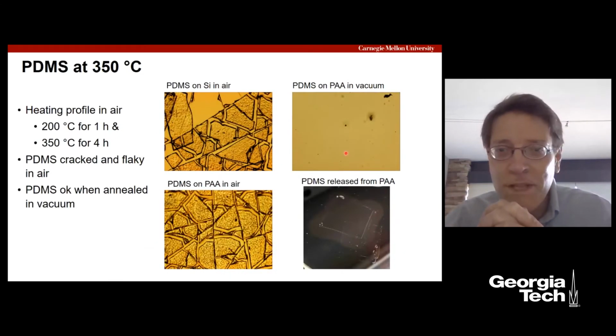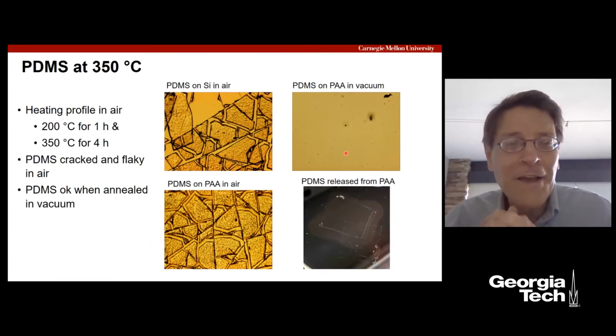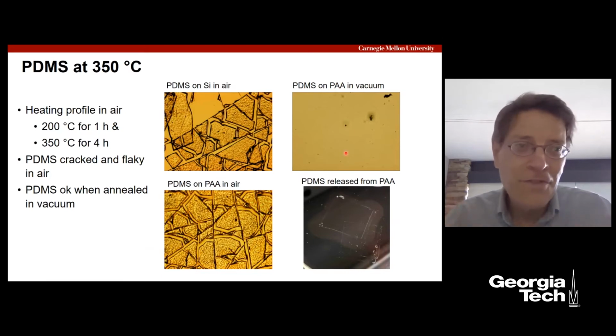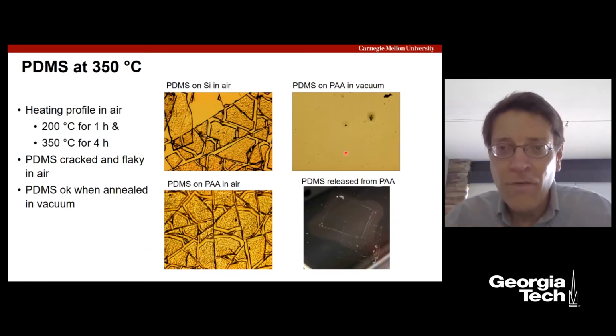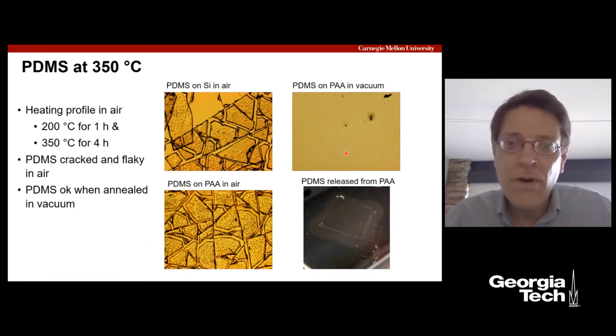The first thing that can go wrong is the PDMS will not work. And so what we found early on was, of course, PDMS, especially the Sylgard 184 that we were using, isn't meant for high temperature. The vendor recommends this gets cured anywhere 60 degrees, 100 degrees centigrade on that order. So we're trying to cure this at 200 degrees C, 350. Why? Because we want to sinter the silver that we were jetting, and also cure the polyimide. Well, when you cure the PDMS in air, it decomposes and it cracks, fractures. It looks like broken glass on the wafer.